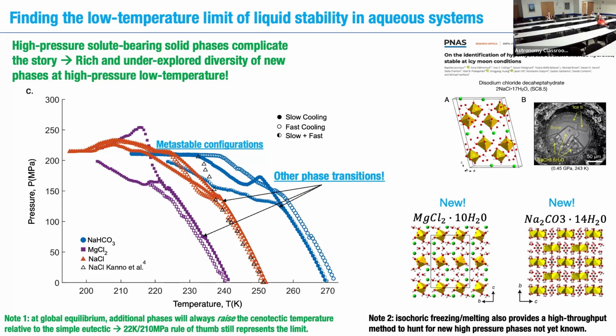And so a couple of things that I'll note to you. One, all kinds of interesting treasure hunting to be done at low temperature, high pressure. Two, the isochoric freezing technique turns out to be a really interesting high throughput method by which to hunt for low temperature, high pressure phase transitions. And then three, just note that these additional phases will almost always raise the cenotectic temperature relative to the pure phase, right? Relative to the simple binary case.